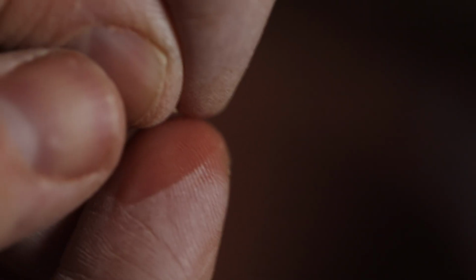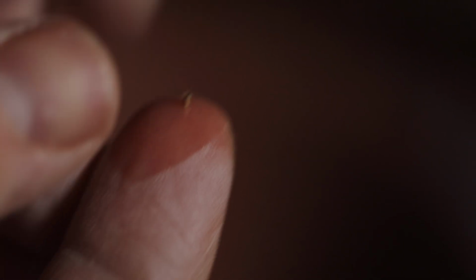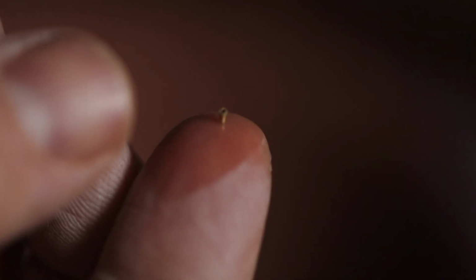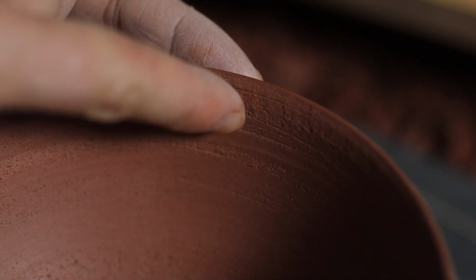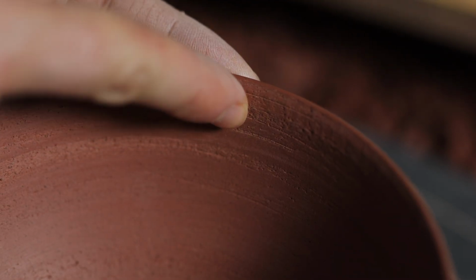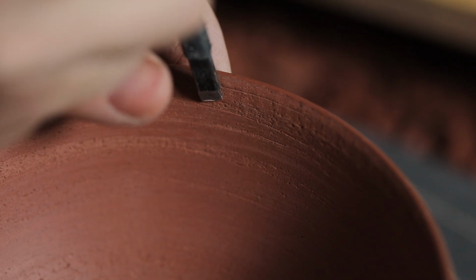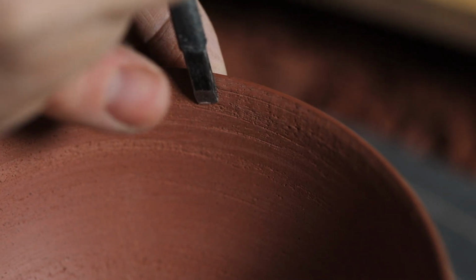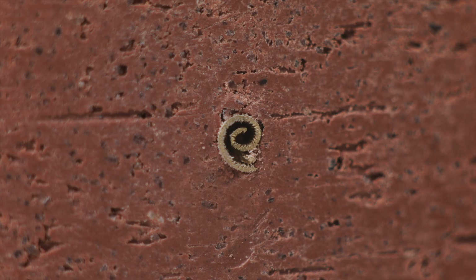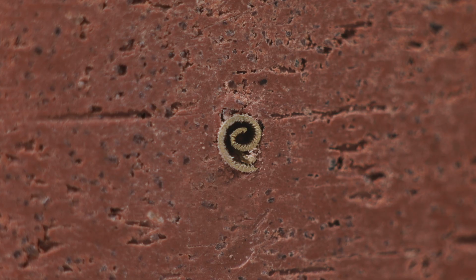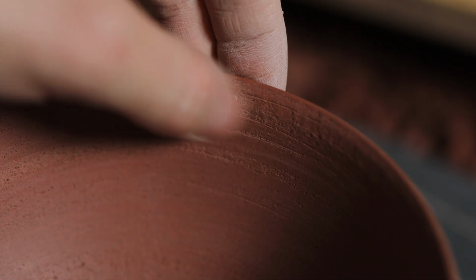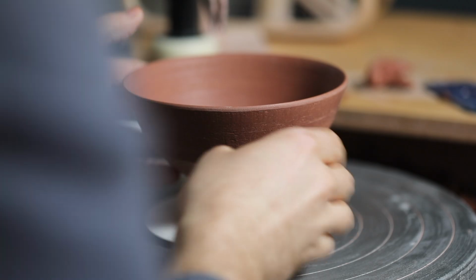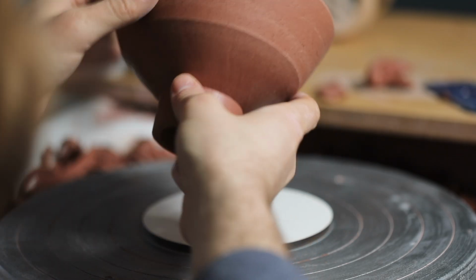I lick my fingertip and then delicately place a piece of bronze onto it, upright. I then lightly press this into the wall of the pot, aiming first to simply tack it onto the surface, and thereafter I use a flat metal edge to fully press it in. It doesn't matter if it leaves a slightly raised bump, it's going to melt anyway, and the glaze I'll cover the pot in will coat it easily.